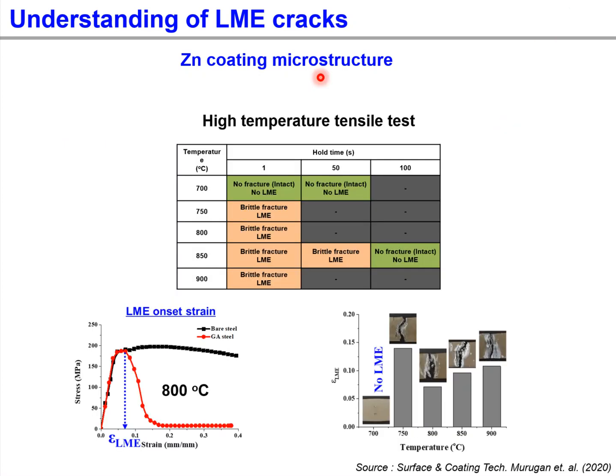To understand the underlying mechanism of zinc coating microstructure, Gleeble tests at different temperatures, starting from 700 to 900 degrees Celsius, with different holding times have been done to correlate between zinc coating microstructure and LME behavior. Specific temperature and holding time combinations show more proneness to LME cracks than others.